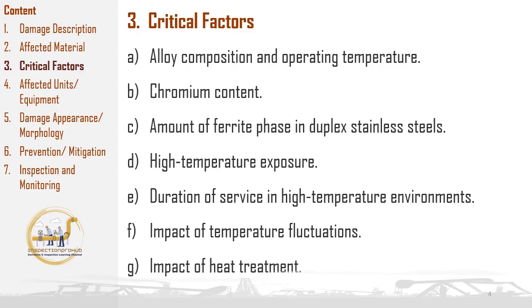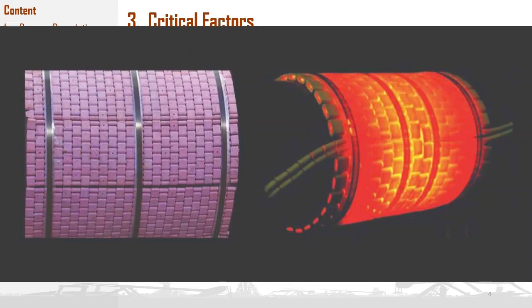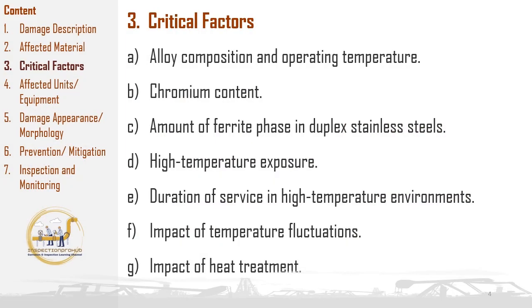The last critical factor is the impact of heat treatment on embrittlement. Heat treatment plays a significant role in the potential for embrittlement in materials, particularly if they are held at or slowly cooled through the embrittlement temperature range. When materials are exposed to this critical range, typically between 600 to 1000 degrees Fahrenheit, and undergo slow cooling, it allows for the formation of embrittling phases, such as the alpha prime phase, which degrade the material's toughness and ductility.